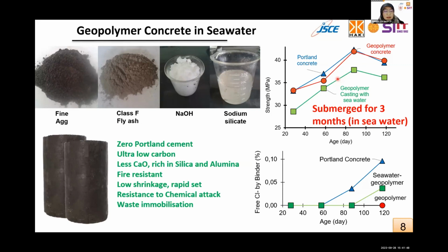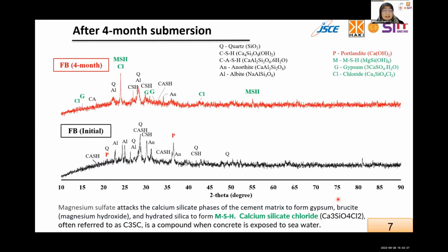And also we can see here in marine area, we put the Portland concrete together with the geopolymer. The red one here, we use geopolymer with tap water, and the free chloride ion in geopolymer is very small compared to the Portland cement. And also, this is one of the abilities of geopolymer to immobilize and act as an adsorbent to chemical ions. And then we have studied that geopolymer is easily attached to the conventional concrete.